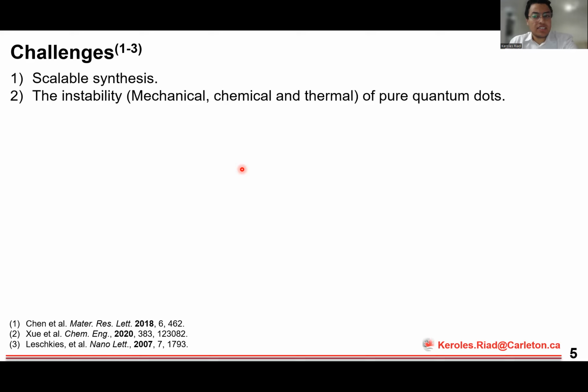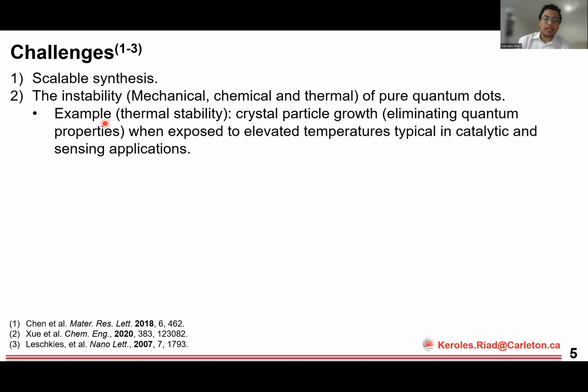The second challenge is that pure quantum dots are unstable mechanically, chemically, and thermally. One example of that is if you have a catalytic or a gas sensing application where those particles need to operate under elevated temperatures, those high temperatures would lead the crystal size to grow. And because the quantized effect is a function of crystal size, that could mean that the crystals would grow beyond the Bohr diameter, and that would eliminate the quantized properties. So this is an example of thermal instability.